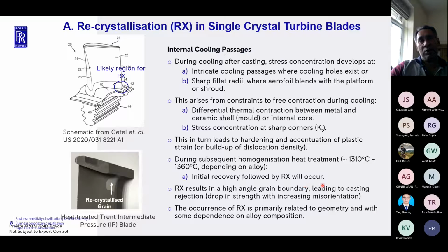Now, this is something you definitely do not want in a single crystal alloy, because in a single crystal alloy, you do not have grain boundary strengtheners. And therefore, if you do have a grain boundary, which is a random high angle grain boundary in the case of a recrystallized grain, you have a dramatic drop in strength. And because of this dramatic drop in strength, you clearly cannot accept this blade in service.